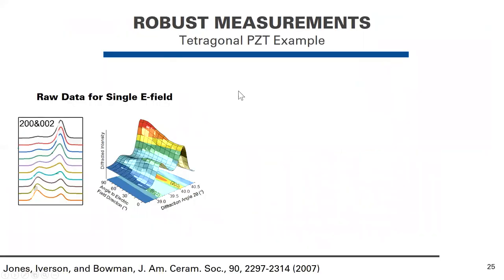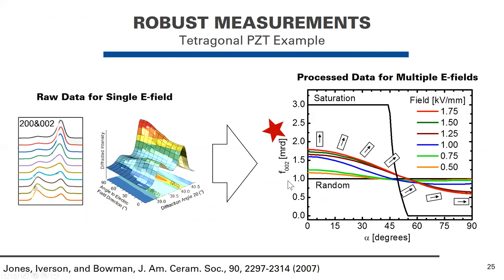So what does this look like? Well, again, raw data looks something like this. If you fit the peaks and do these calculations, you can create pole figures. Here, represented on the y-axis, is the multiple of a random distribution of the 002 pole as a function of angle. And in this particular example, we were applying an increasing field amplitude. And so you can see the evolution of these pole densities as a function of electric field and angle.